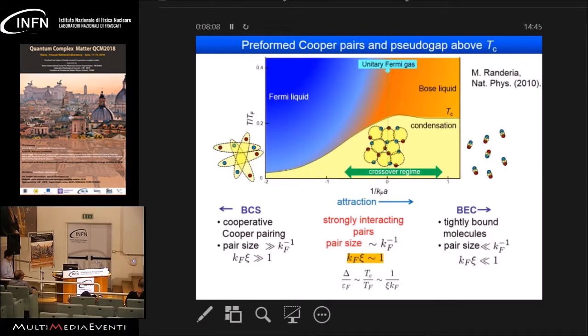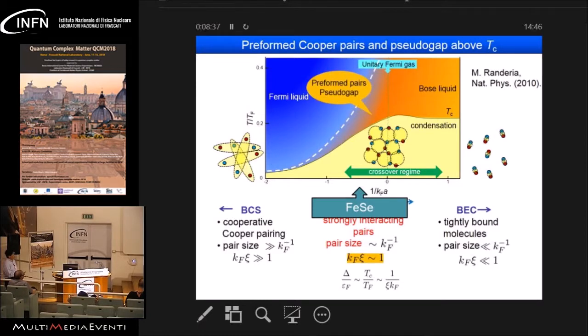So we can safely say that this iron selenide is located deep inside the crossover regime between the BCS and BEC limits. So this is quite an important material to look at this BCS-BEC crossover. And one important thing is that the so-called pairing temperature deviates from the Tc on this side. And we expect an extended temperature regime in which we have the so-called preformed pairs, or you may expect a sort of pseudogap. So we want to look at the evidence for the preformed pairs, first of all.